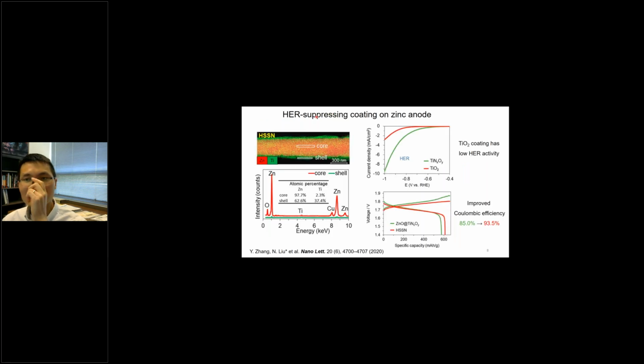A second work I want to talk about is suppressing hydrogen evolution, because hydrogen evolution is a competing reaction with the zinc redox reaction. So we want to suppress the side reaction. We evaluated different coating materials on the zinc and found that certain materials that have low catalytic activity towards hydrogen evolution result in a higher Coulombic efficiency of the zinc anode.